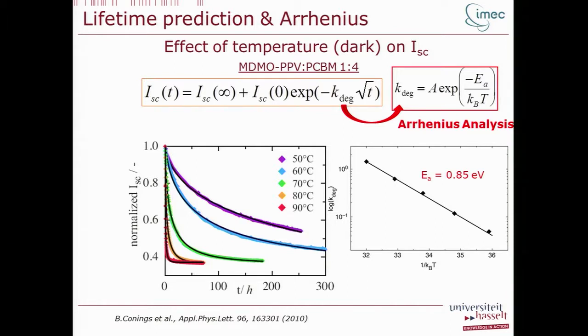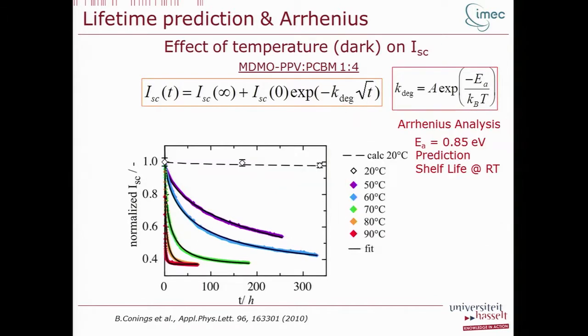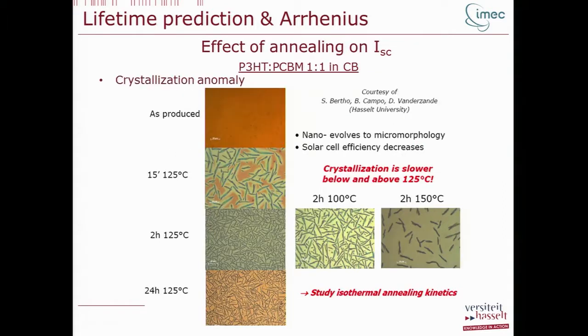But the idea is that you could also do prediction to another temperature. So if you do a prediction to room temperature, for example, this would be the curve that you get, and the points on top are the points that we really measured. So this gives you an idea of how this approach can be used to do lifetime predictions. You could also go the other way around. You could say, let's predict what happens at 120 degrees Celsius, at 150 degrees Celsius, and so on. But there, you have to be careful that Arrhenius is only valid in a given temperature window. And that's what I would like to illustrate in the last slides.